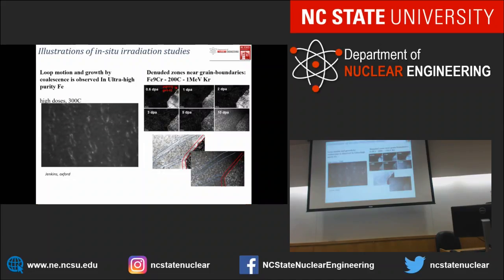So here I can show you two examples. On the left, the first example is in situ ion irradiation in pure iron at 300 degrees C. As you can see from these videos, the defects created by the irradiation appear as white dots, and the accumulation of these defects forms large dislocation loops. And some of the loops further interact with each other, resulting in the coalescence of the loops.